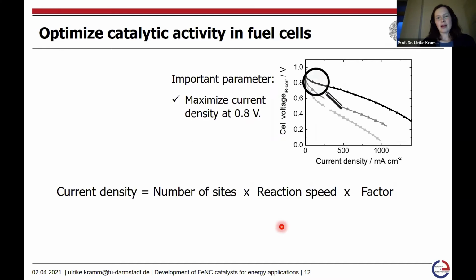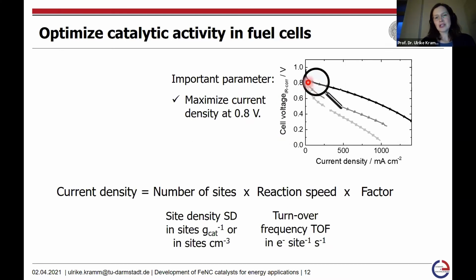I already mentioned that the maximization of the current density at 0.8 volts is one of the targets for fuel cell application. If we would like to do so, we need to understand how the current density is developed. The current density by itself is basically a product of the number of active sites and the reaction speed. And then there is also a proportionality factor. Based on that, we have two real chemical numbers, that is the site density and the turnover frequency, that determine the current density that we can achieve.